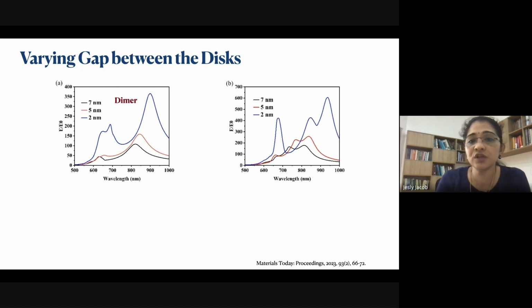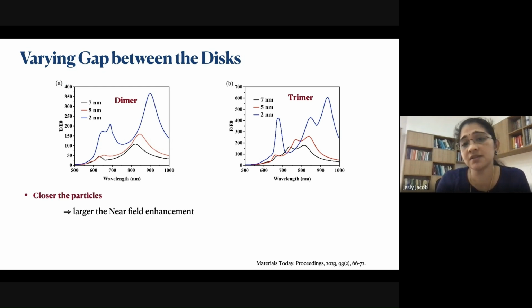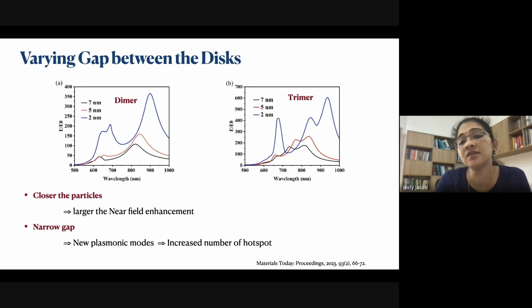And again, moving to the trimer structure, you can see that when the gap size decreases, that is when the discs come closer, larger field enhancement is happening, and with the narrower gap, new plasmonic modes and an increased number of hotspots appear, which means that it will improve the sensitivity much more.